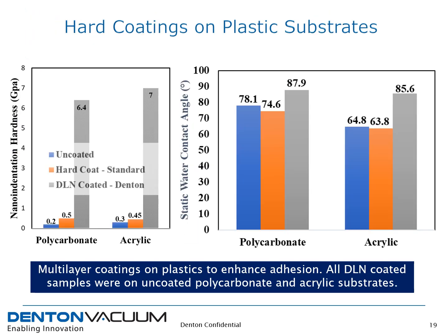On the other hand, using higher ion energies, hard coatings could be obtained on plastic substrates, for example. The goal here was to increase the hardness of plastic surfaces for application in abrasion-resistant coatings for automotive transparencies. In order for these coatings to have good adhesion to the plastic substrates, a multi-layer coating was deposited by changing one or more process parameters.